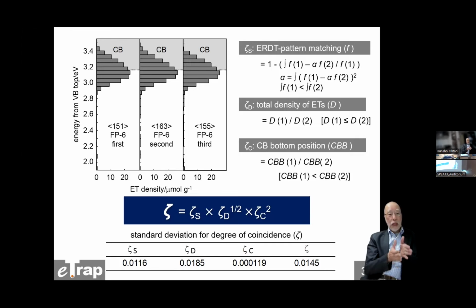And to check the similarity of those patterns, we use 3 parameters. One is the ERDT pattern shape matching. That is the shape of the peak, not the absolute value. The second one is the total density, zeta D. And the last one is the conduction band bottom position. By putting in weights, the total degree of coincidence, the zeta value, is calculated from this equation.